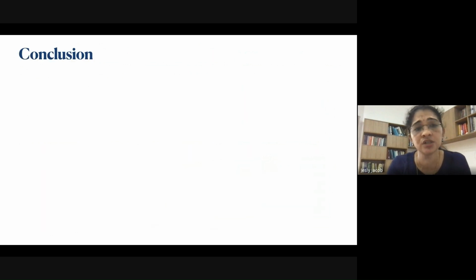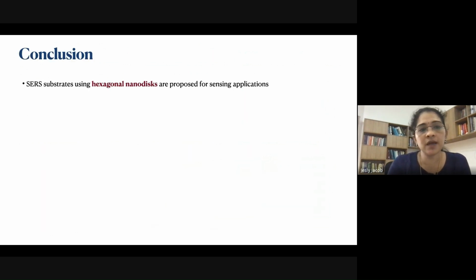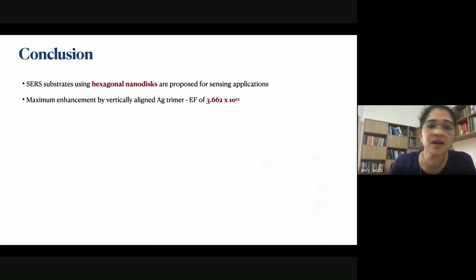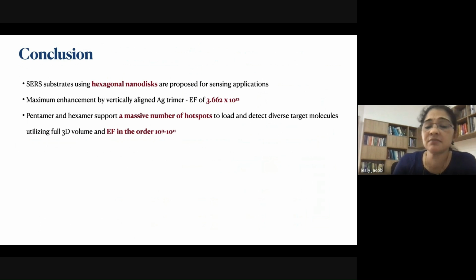So in conclusion, we have proposed a SERS substrate. It is already published work. Hexagonal nanodiscs are proposed for sensing applications. And the maximum enhancement by vertically aligned silver trimer is 3.662 × 10^12. And pentamer and hexamer, you can see that though the enhancement factor is a little less than silver trimer, it